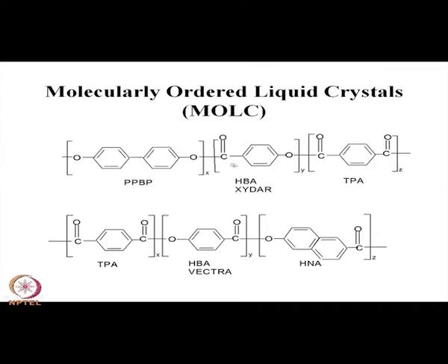So, this liquid crystalline phase occurs due to the rigid rod like configuration of the molecules. When such units are present in that polymer, those units are known as mesogens. If those mesogens are present, then that gives long range order in the liquid phase.